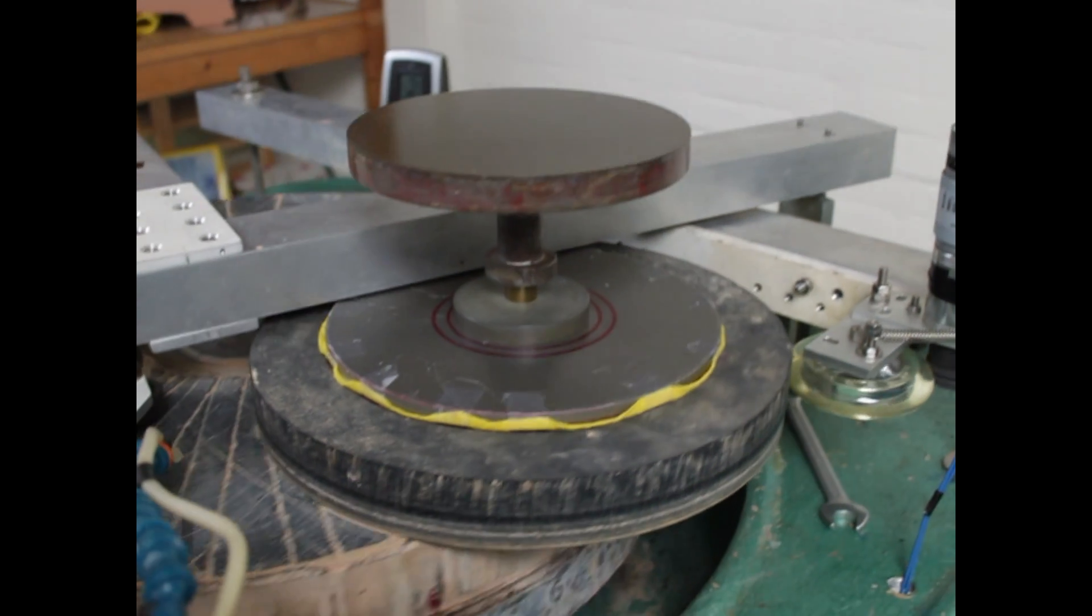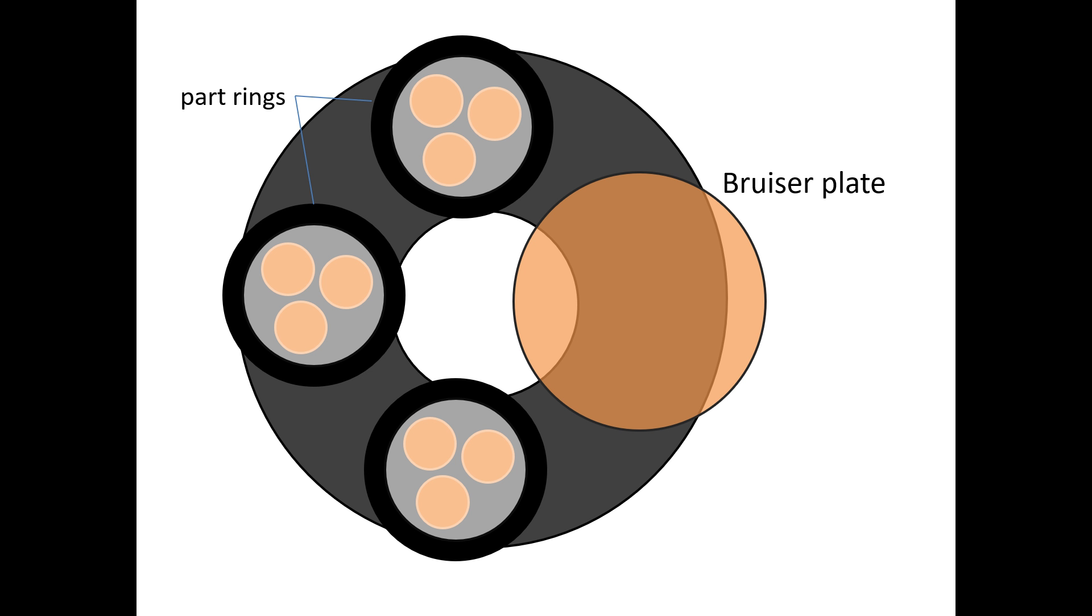In the meantime, the pitch surface also performs abrasive action on all the surfaces in contact with it. So these will all gradually assume the shape opposite of that of the pitch surface. This also includes the shape of the bruiser and of course numerous other objects that we can simultaneously polish flat against the same pitch surface. So to set up the machine and to achieve an acceptable flatness for the pitch takes quite a lot of effort.